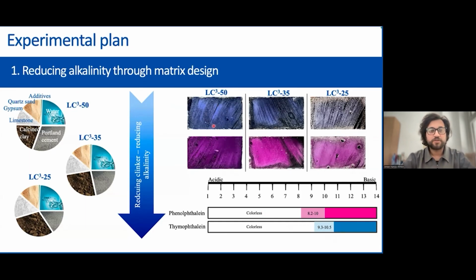Again, if you look at these top pictures, you see LC350 and LC335 show dark color, while LC325 shows a very light color with thymolphthalein. And this is the same case with the phenolphthalein indicator. So at least for LC325, we can conclude based on these indicator results that the alkalinity level in this matrix is somewhere between 9.3 and 10.5, which is quite low considering that for pure Portland cement, alkalinity levels can be around 13.6.